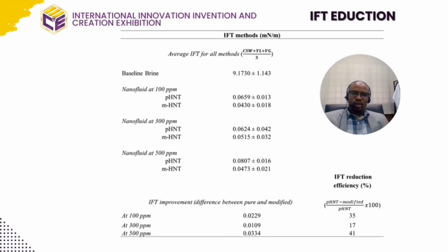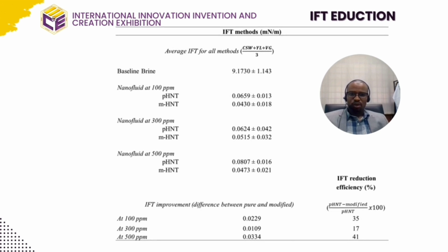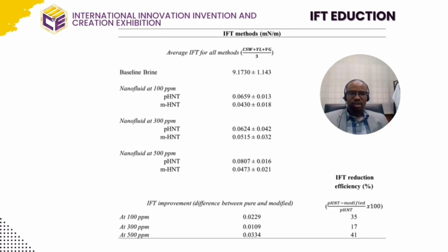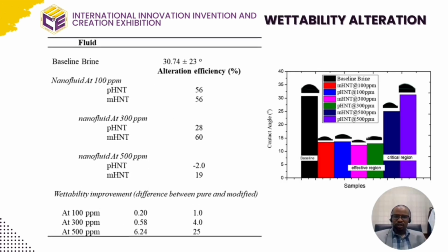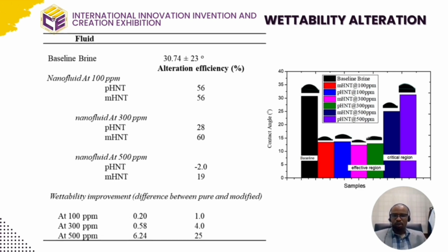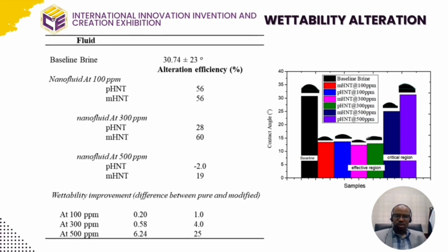Investigation into the interfacial tension reduction revealed that the modified halloysite nanotube reduced the interfacial tension significantly better than the pure halloysite nanotube, and about 41% improvement was observed at 500 ppm concentration. Similarly, the wettability alteration investigation revealed that the modified halloysite nanotube reduced the contact angle, which is one of the important properties to release crude oil from the reservoir. So this showed that the modified halloysite nanotube has more effect than the pure halloysite nanotube.